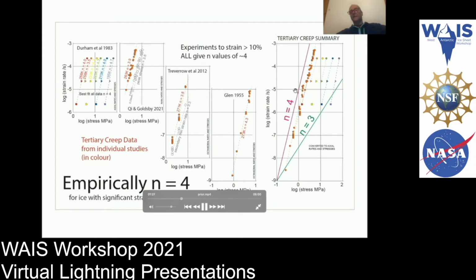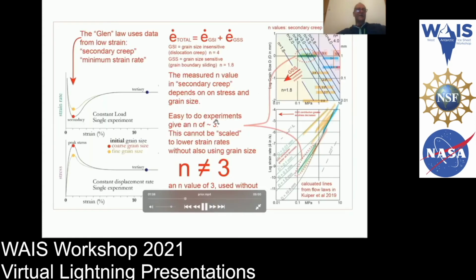This is a summary plot of some of the data, and you can see n equals 3 really does not fit. N equals 4 does fit the data. So let's unpick a little bit where n equals 3 comes from. The Glen flow law uses data from very low strain, what's called the minimum strain rate or secondary creep. The equivalent in a constant rate experiment would be the peak stress. And that's important because the grain size hasn't changed from the starting grain size.